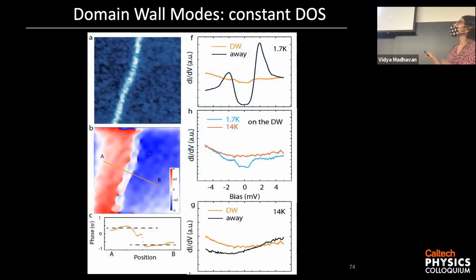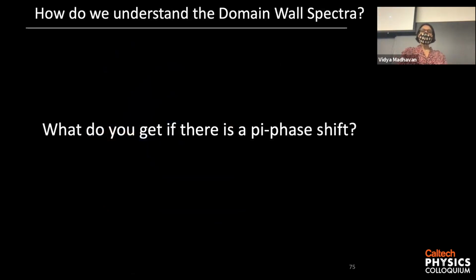So this flat density of states, it actually disappears above the superconducting transition. So above TC, you get this orange spectrum. So this is a property of the superconductor. And the actual spectrum away from the domain wall and at the domain wall are not that different. So this is not a simple density of states effect. So the question is, what is this?